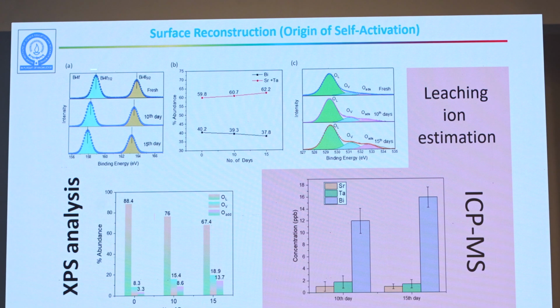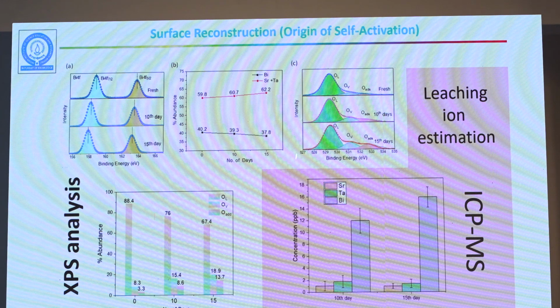Okay. Now you look at this XPS analysis. In XPS analysis, what you see is that the amount of bismuth is going down slowly, showing that actually bismuth is going from the surface. Similarly, you can also see, 3 minutes, I'm done. So here also you can see this is an oxygen peak. Again, without going into the details, what you can see is that the green peak is coming down, but the other peaks are actually coming up. The other peaks are water molecules or oxygen getting absorbed on those vacancies. So both of them show that bismuth is gone, oxygen is gone, and other oxides, water or O2 is getting absorbed on the surface.